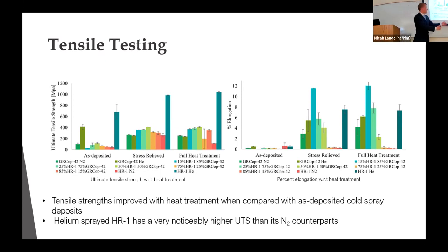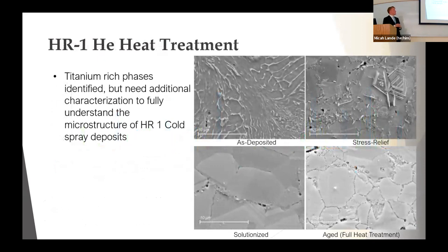But as we go through the heat treatment process, especially with the copper alloys, we can see that elongation develops much better. We get much better percent elongation from the tensile tests. However, as I said before, that percent elongation for all the samples is definitely lower than what we would want, especially when compared to direct energy deposit. Again, I keep going back to that for an example of a thermal additive manufacturing method. So higher strength, a little bit less ductility in our samples, but that's the trade-off going on there. From there, we can also see, as we go through the heat treatment process, our microstructural changes. This is our HR1 helium sprayed.